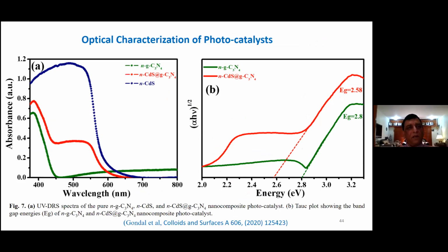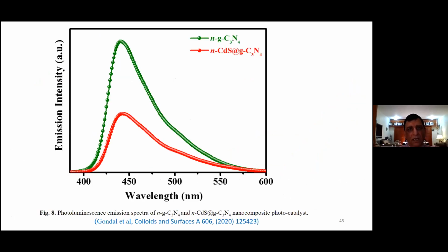And then finally, we do UV diffuse reflectance spectra through the Kubelka-Munk function. We can calculate the band gap energy of this catalyst that we produced. So you can see the band gap has shifted toward the visible light because it has decreased. And we know that the energy is inversely proportional to the wavelength. So we reach the visible light.